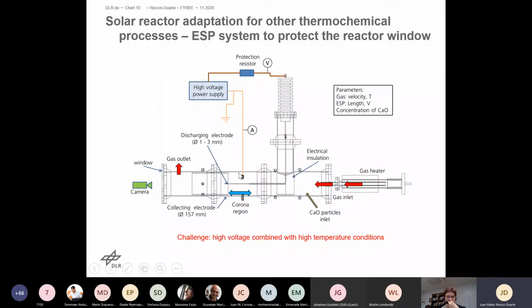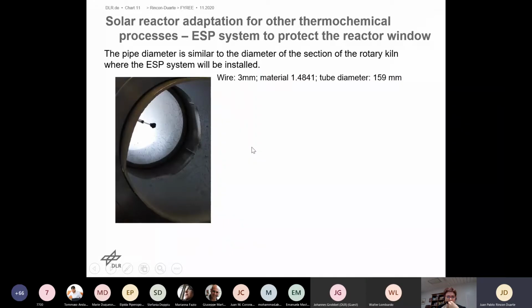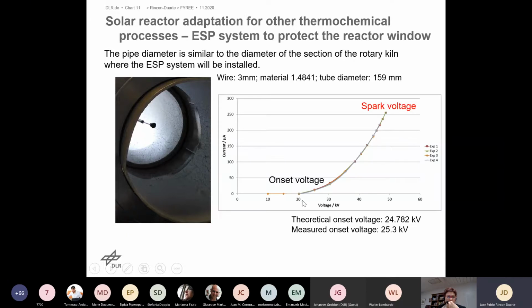The two parameters to characterize these systems are the current, which is circulating through this collecting surface, and also the voltage, which is applied to the discharging electrode. So until now, we have tested the experimental setup at room temperature. Here we can see the inner part of this tube. This white material is the electrical insulation for high temperature, and this uncovered metal surface is the collecting surface. This is the electrode, and we measured the voltage and the current. For this geometry, which is very similar to the geometry where we are planning to install this system to protect the window in the reactor, the charging process starts at about 24 kilovolts, and if we increase the voltage, the current will increase also, and so will the removal efficiency of the system.